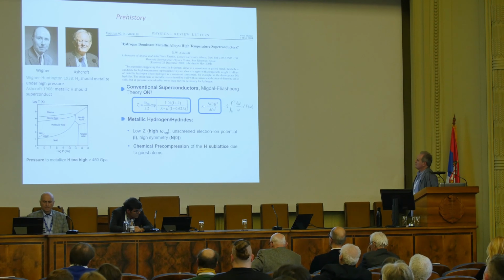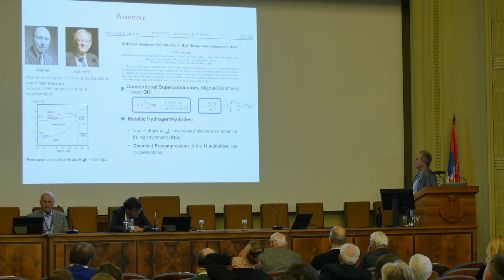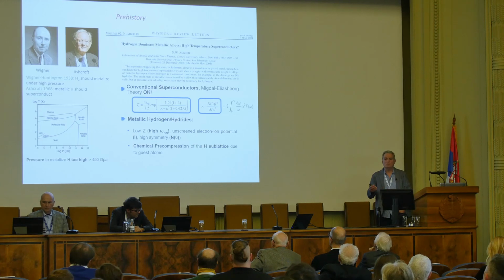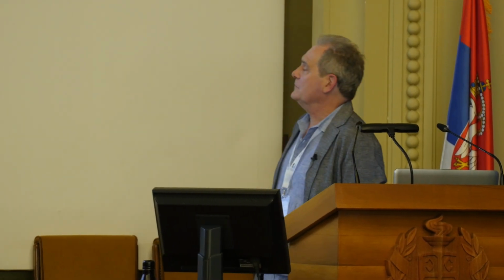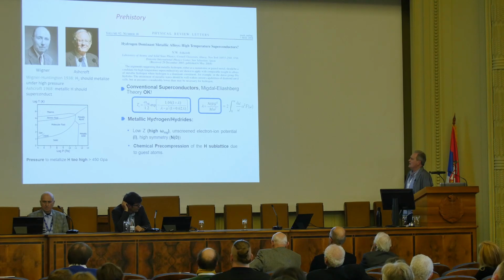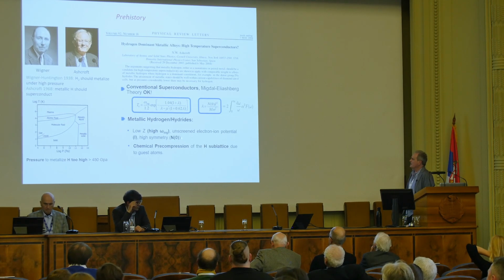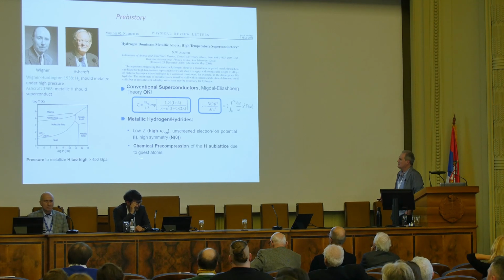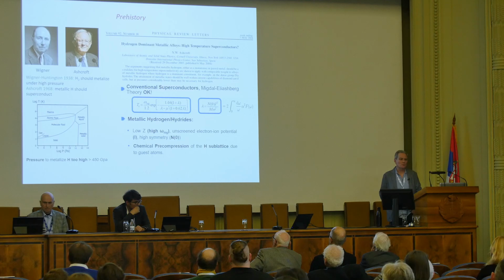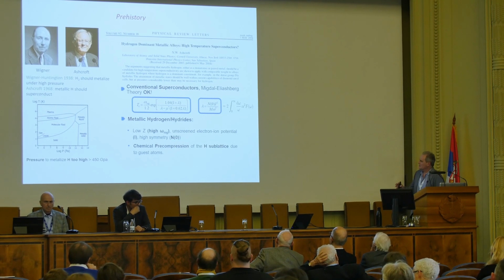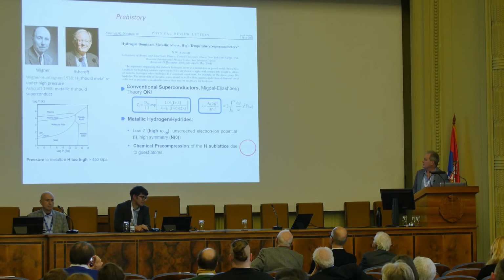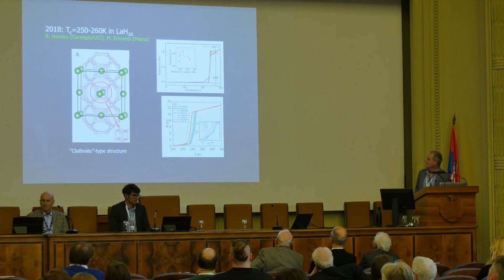And the strength of the pairing comes from this function, which is called alpha squared F, the electron-phonon spectral function. It weights the phononic frequencies with the matrix element, which is calculated for each phonon with the electronic system. And basically, the recipe that he came up with was that you should have high omega log and an unscreened electron-ion potential, and potentially chemical pre-compression of the hydrogen sublattice, meaning let the chemical pressure do some of the work for you so you don't have to go to these very high pressures. It's a little oversimplified, but that was the message that the community took away, I think. I'm going to come back to this alpha squared F a little bit later.